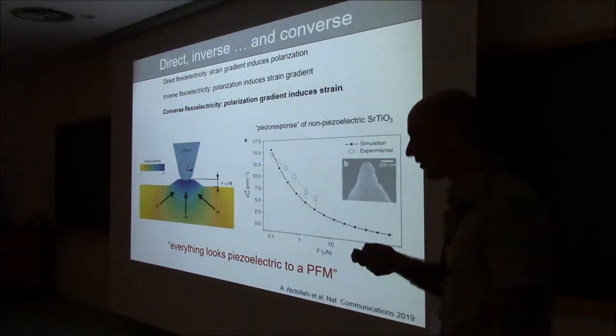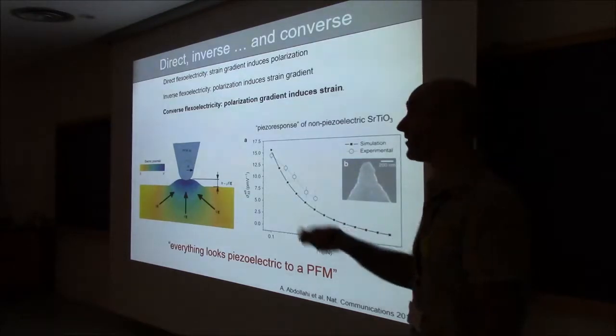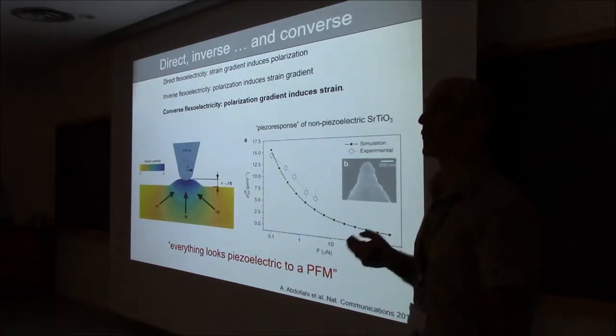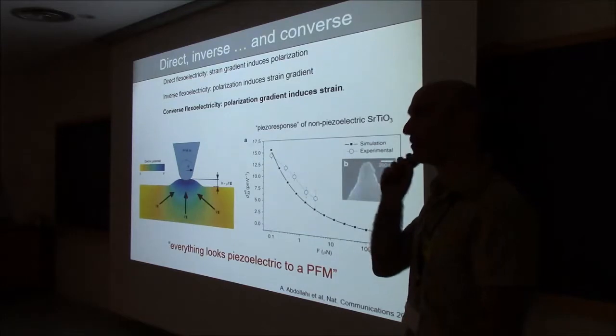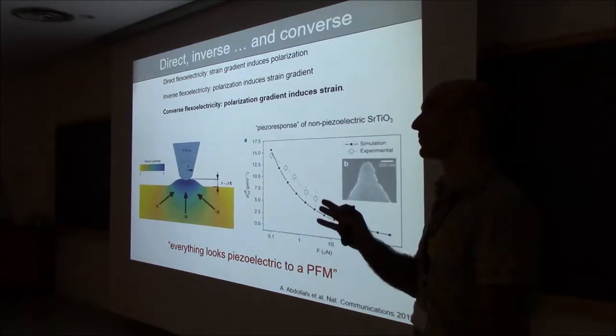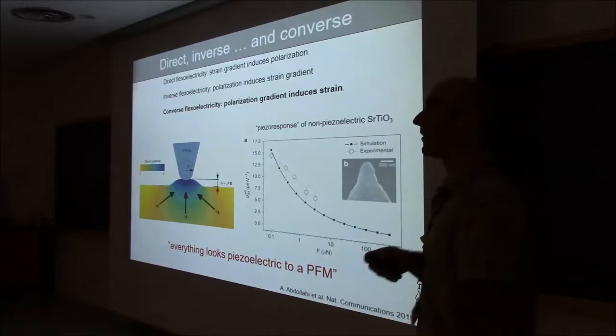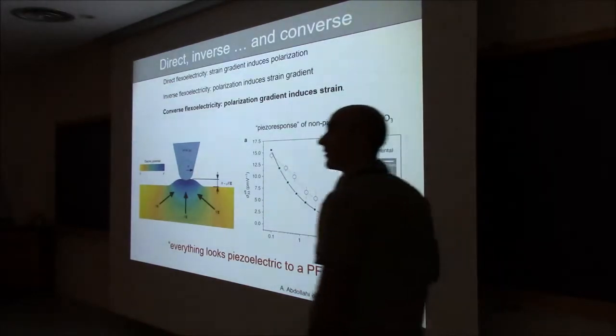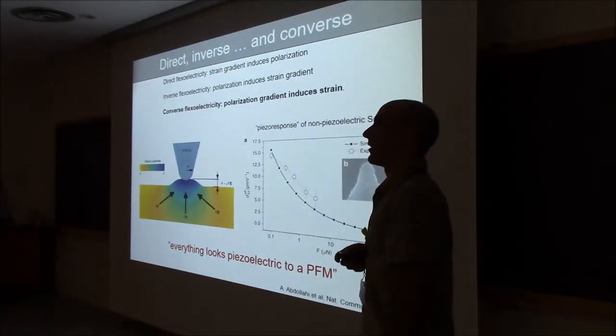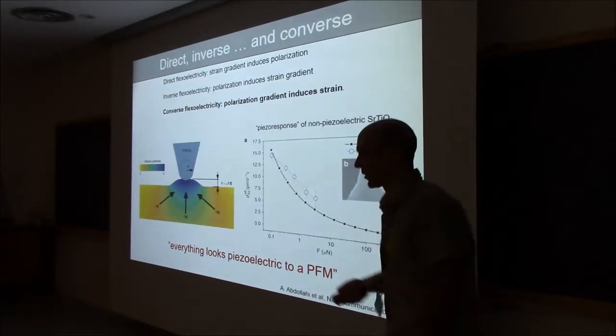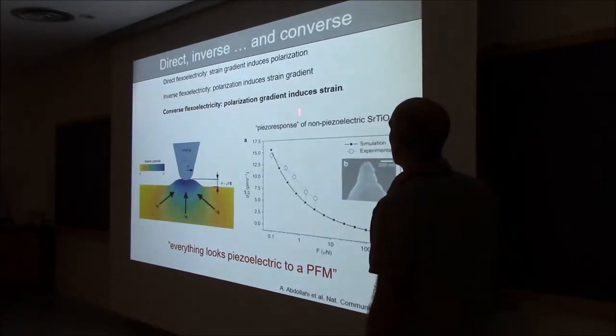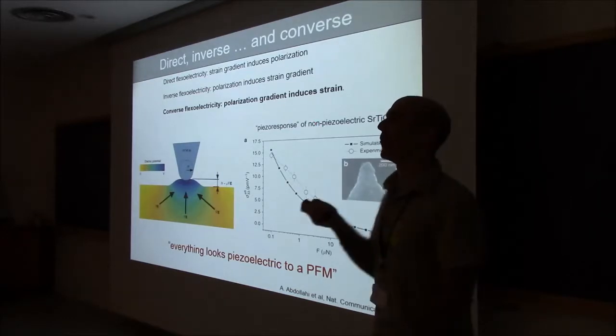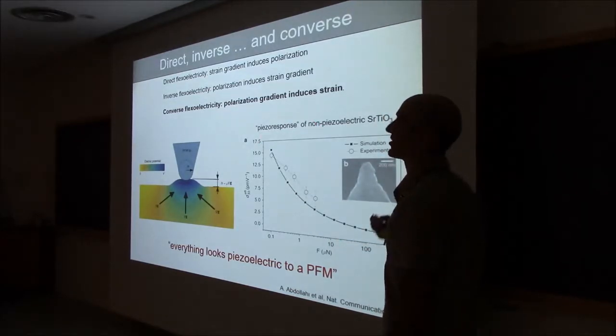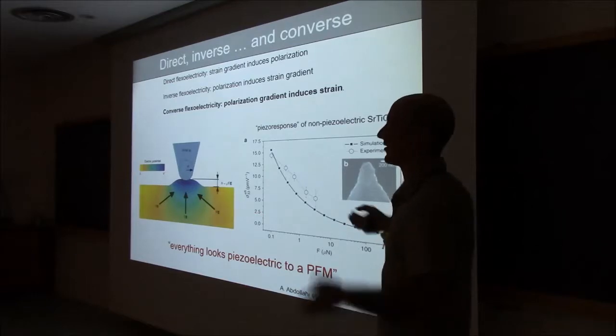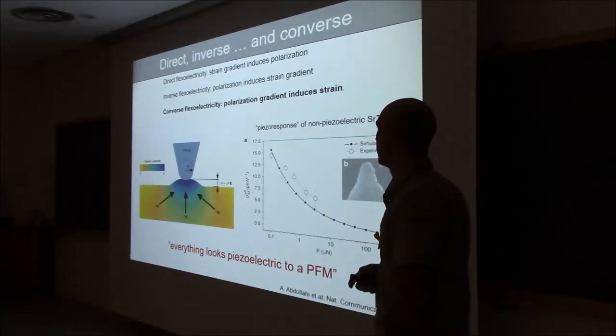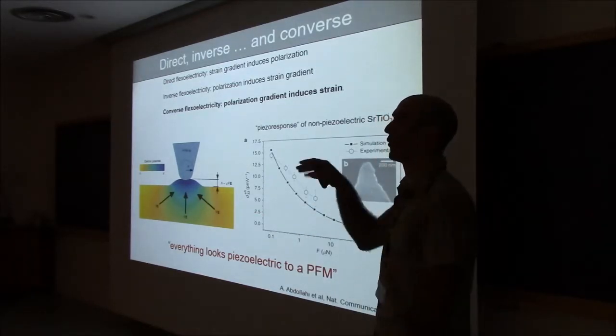So as they say, if you're a hammer, everything looks like a nail. If you're a PFM, everything looks piezoelectric. Okay, so never use just PFM to determine whether something is piezoelectric or not. So does the polarization gradient induce a homogeneous strain, or is there also a strain gradient? Well, okay, so the definition is a linear polarization gradient will give you a homogeneous strain. However, the polarization gradient is never linear. In this case, it's radially decreasing. So yeah, the strain itself will not be perfectly homogeneous.